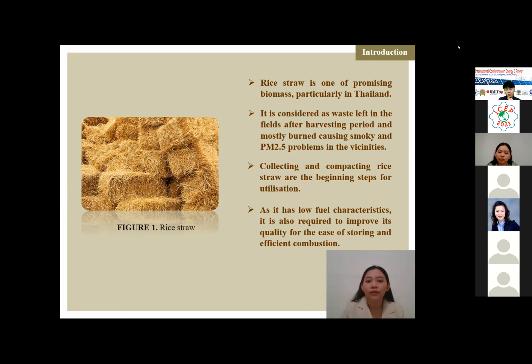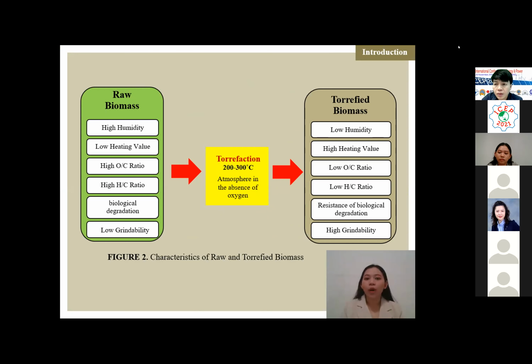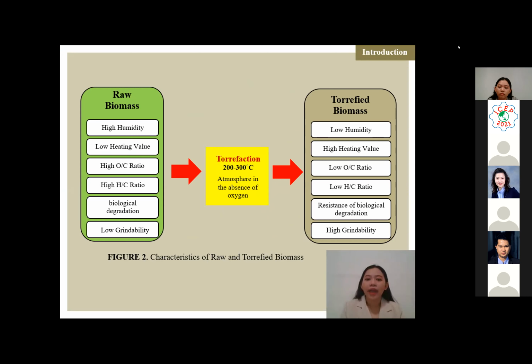Moreover, as it has low fuel characteristics, it is also necessary to improve its quality for ease of storing and efficient combustion. Therefore, upgrading rice straw by a thermochemical process called torrefaction is of interest. It is a process using a temperature range of 200 to 300 degrees Celsius in an air-absent environment for removing moisture content and light volatile matter from the rice straw. As it is under low temperature, the main product is commonly in solid phase and called torrefied biomass. Torrefied biomass has low moisture content and low oxygen-to-carbon and hydrogen-to-carbon ratios, resulting in higher heating value. Moreover, torrefied biomass can improve grindability and resistance to biological degradation.